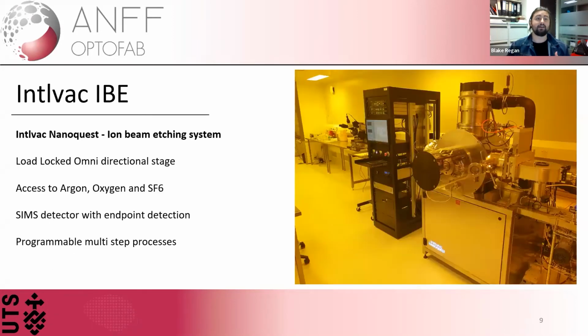system. So we have an ion beam etching system, and it does have the capability of chemically active ion beam etching. This system also comes with a load-locked omnidirectional stage, which means that you can do any amount of tilted etching of samples, going forward and backwards, and also rotating the sample. This allows processes such as undercutting of, well, if I use my own research as an example, photonic nanostructures, but also allows other areas such as tilted gratings, including some metasurface materials, as associated with the secondary group here that we have at UTS, the TMOS group.